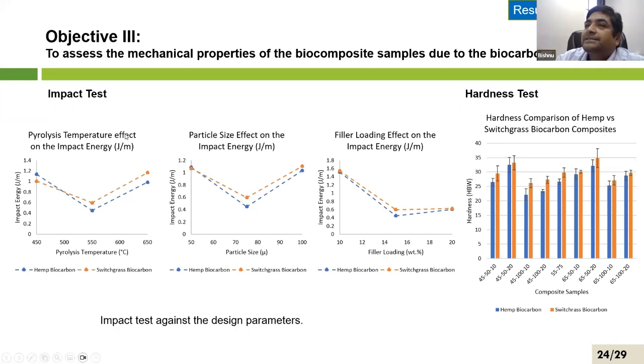So the impact test, again, we found that 550 has a lower impact, or requires a lower impact energy, as compared to 450 and 650. This is something that we're still trying to understand, what is happening there. Interesting, with that 550 biochar.